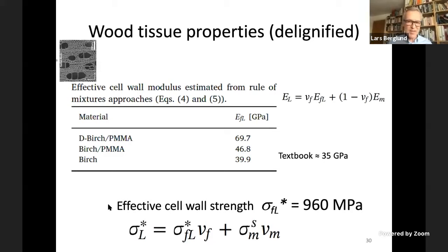The interesting thing is when we analyze the properties of the wood tissue itself. If we just analyze the properties of the solid wood tissue, and we use conservative micromechanics models, neat birch gives a modulus of 40 gigapascal. If we then impregnate with PMMA, the effective modulus of the cell wall is 47. So in other words, we transfer stress in a much better way. And if we delignify, we do even better. We reach an effective modulus of 70 gigapascal, partially because we have higher cellulose content, but we also have much better stress transfer. And if we calculate the intrinsic cell wall strength, it is as high as 960 megapascal. So it seems our wood materials are much better than we've thought in the past. And of course, the reason is that we have so much inhomogeneity when we use it as a porous material.